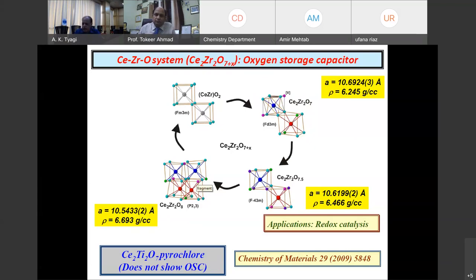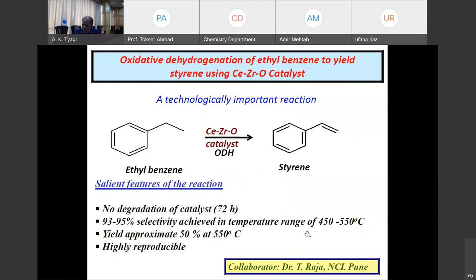This is very important. And of course, my friend from NCL Pune used this compound for catalysis. He used it for what is called the oxidative dehydrogenation reaction. The ODH reaction is used to introduce unsaturation in organic compounds. So ethylbenzene, you can convert to styrene by knocking out hydrogen from here. You introduce a double bond, as you can see here.